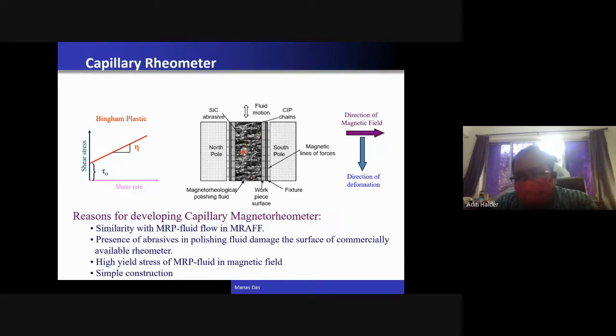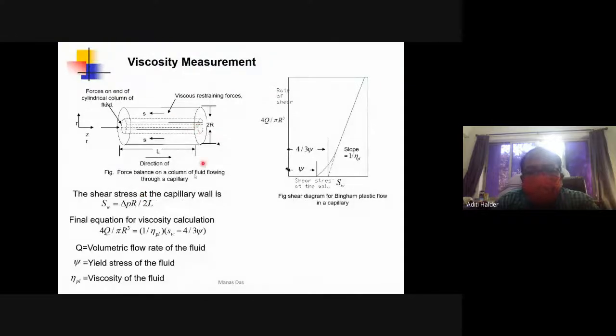Now, you can see the equations here. This is the shear stress at the wall, and this is the shear rate. R is the radius of this capillary, and Q dot is the volumetric flow rate. Eta PL is the plastic viscosity, and the shear stress at the wall can be calculated from the pressure gradient. At the wall it is the radius, and L is the length of this capillary where we have applied the magnetic field.